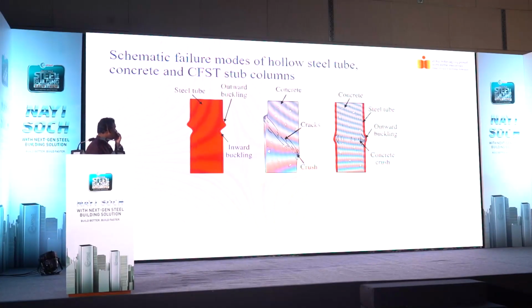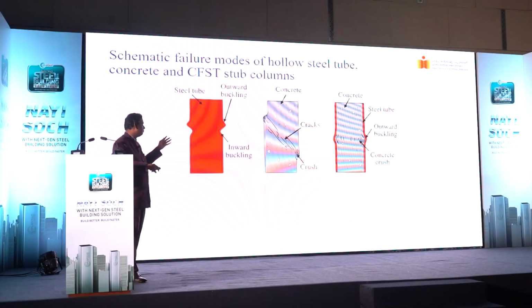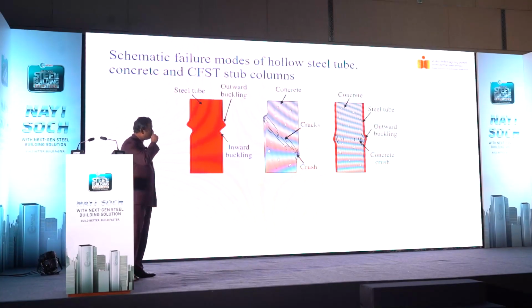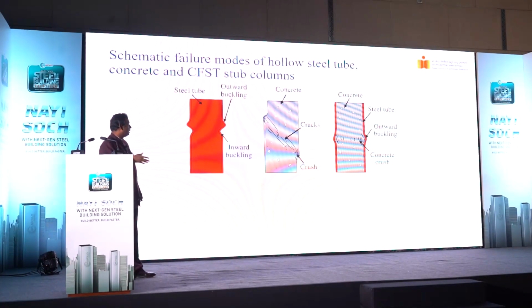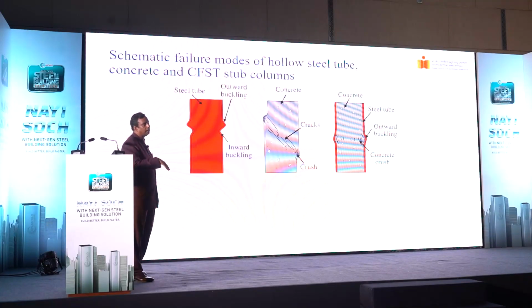So you have this inward and outward buckling. This is a steel tubular structure, but if you have regular concrete, then you have this crack and crushing that takes place at 45 degrees. But when you add the two together, you drastically reduce your inward buckling. The only possibility is an outward buckling, so it is a much improved failure mechanism simply by adding concrete. Okay.